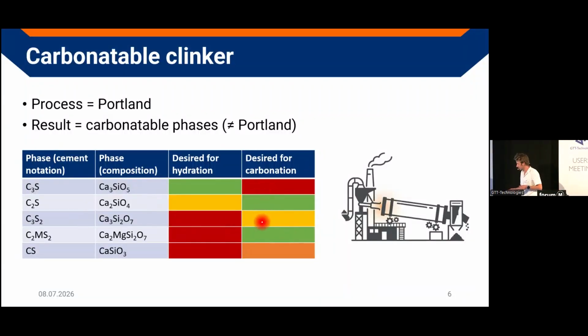We see that the reactivity for carbonation of the wollastonite is rather low, especially compared to the other calcium silicates. Which means if you add a little bit more calcium, okay, you need more calcium carbonate, but you gain it in the carbonation process further. So the more calcium carbonate you put, you can store even more than the extra you put afterwards if you go towards the C2S.